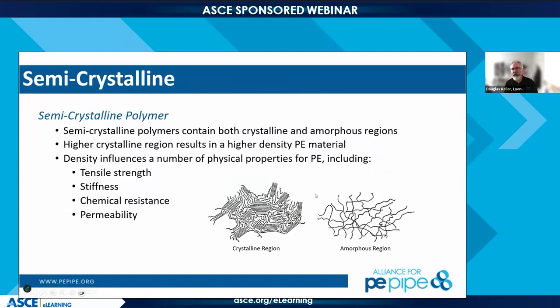All right, so I talked about semicrystalline before. Again, the crystalline regions give the material its density. And density is related to the tensile strength of the material. The more dense the material, the higher the tensile strength, the higher the stiffness of the material, the more chemical resistance you have. If you think about, if you're a chemical and you want to get through that image on the left, that's a pretty tortuous path. That's like driving through New York City. However, on the right, if you're a chemical and it's all the amorphous, it's pretty easy to get through. That's like driving through West Texas.